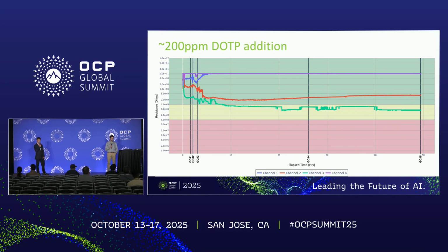The BGA and QFP components, channels 2 and 3 respectively, responded much more drastically. It's likely that the larger surface area of these components played a role in this. When the distillation was initiated, some of the resistance values recovered while some merely stabilized. It's likely that some contaminants were left under those component packages at the end of testing.